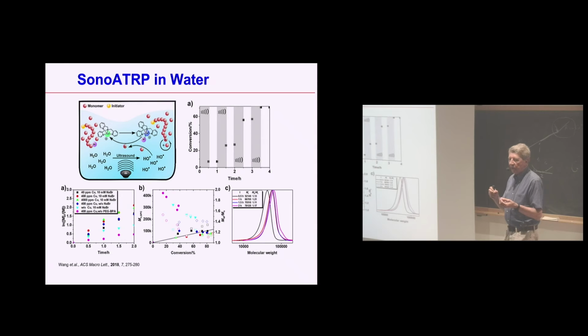Because ultrasound, in the presence of water and a small amount of oxygen, can generate hydrogen peroxide, which would generate hydroxyl radicals. So you don't need these piezoelectric particles at all, because these hydroxyl radicals will generate new chain radicals, which reduce copper-2 to copper-1 by taking this halogen atom and generating the corresponding activator species. So ultrasound on, off, on, off, on, off. It is also very important that because you work with such a low concentration of copper, it's enough to switch it off and polymerization stops.